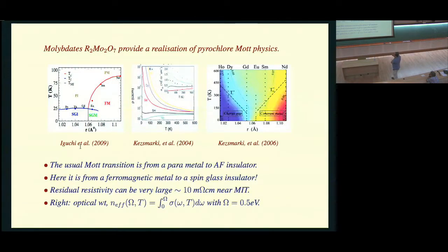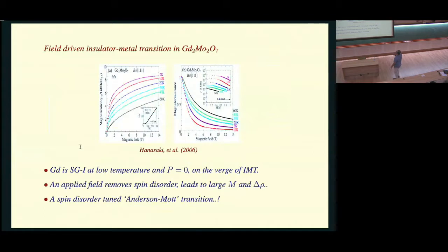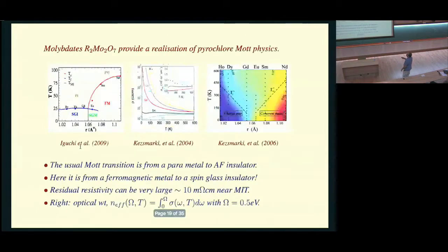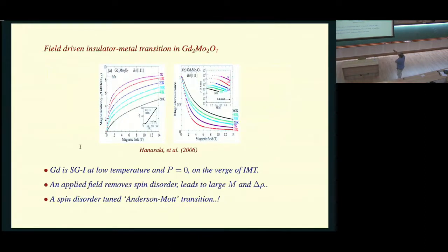Now the usual Mott transition, the usual in the Hubbard language, is from a parametal to an antiferro insulator. Here it is from a ferro to a spin glass insulator, residual resistivity, etc. So you can also, unusually for a Mott insulator, see a field-driven transition. If you were to look at this object, which is on the verge of the insulator-metal transition, and apply a magnetic field, you get a huge magnetoconductance. In fact, the resistance, this is the 10K resistance, falls by a couple of orders of magnitude. That is again because you're in proximity to a ferromagnetic phase, and the phase competition is tilted in favor of magnetic order when a magnetic field is put in.